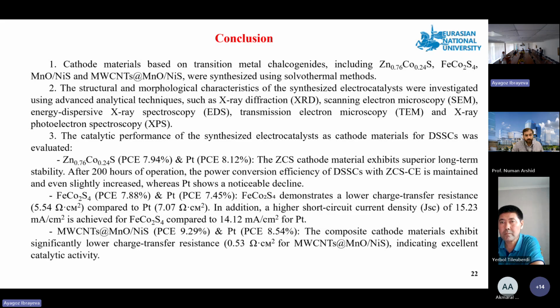The catalytic performance in DSSC shows that zinc cobalt sulfide reached 7.94% versus platinum 8.12%. This is decreased only by 2.2%, but it has good stability. Iron cobalt S4 shows an efficiency of 7.88%, versus platinum 7.45%.